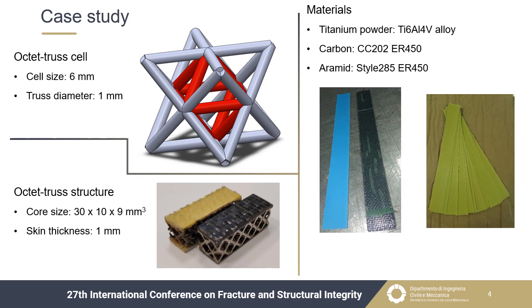The lattice core had a section of 10 mm by 9 mm and a length of 30 mm, while the skin thickness was equal to 1 mm for both types of material considered. This similarity was important for performing a meaningful comparison between the different types of specimens.